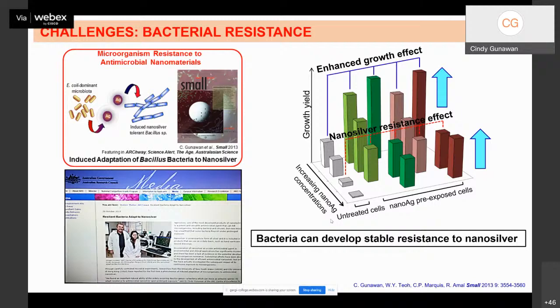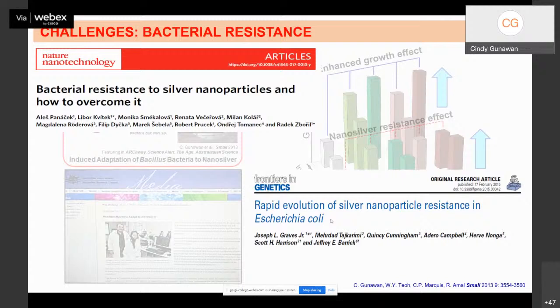We found the phenomenon of bacterial resistance to nanosilver in an environmental group of bacteria called Bacillus. So this Bacillus, following prolonged exposure to nanosilver, was able to develop a stable resistance trait to silver nanoparticles, such that after the prolonged exposures, the bacterium was able to proliferate at an otherwise toxic nanosilver concentration. And since our discovery in 2013, other scientists have also confirmed the development of bacterial resistance in other bacteria: in 2015 in E. coli, and in 2018 in Pseudomonas aeruginosa. Both are gram-negative bacteria and they are clinically important.